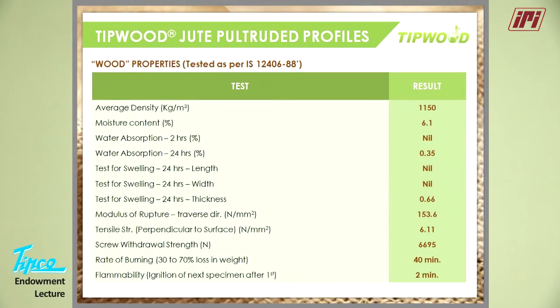density is slightly higher than wood. It's about 1.15 to 1.2 on an average. The moisture content, since it is a phenolic resin, there is going to be some moisture in it. We use jute, which is also a hygroscopic material, so there is an inherent moisture of around 6% in it. But the moisture absorption in 2 hours is nil according to this test. In 24 hours is only 0.35. Then we have done tests for swelling, where we found that it is nil.